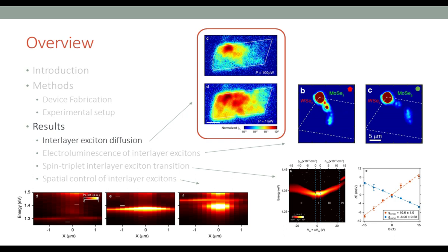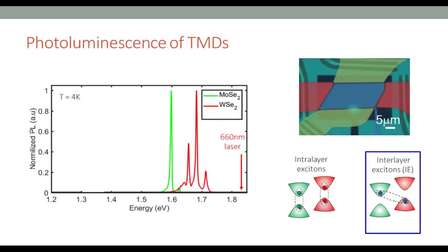So I'll talk about our interlayer excitons and how we measure their diffusion. All of our measurements are photoluminescence. We excite with 660 nanometers, above the excitonic gap of our material. And if you collect from either the WSe2 or MoSe2 monolayer regions, you can see these peaks at 1.7 and 1.6.